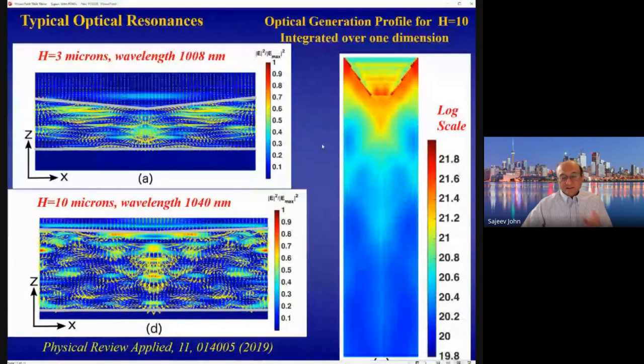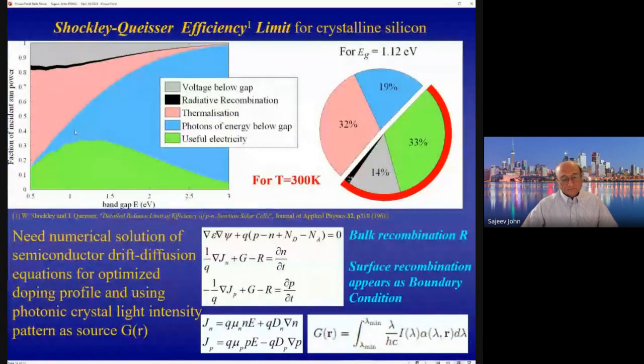And to determine the efficiency of the cell, we have to determine how efficiently these photogenerated carriers can reach contacts that have been placed in the cell. So again, this is the Shockley-Queisser picture showing the maximum thermodynamic efficiency at room temperature, slightly below 33, or it's actually 32.3% for silicon. And we certainly can't absorb all of the sunlight, but with light trapping, we can absorb a fair amount of the available sunlight. And now we have to describe how electrons and holes move or migrate once they are generated. And that is described by means of what are called the semiconductor drift diffusion equations, which are listed here.